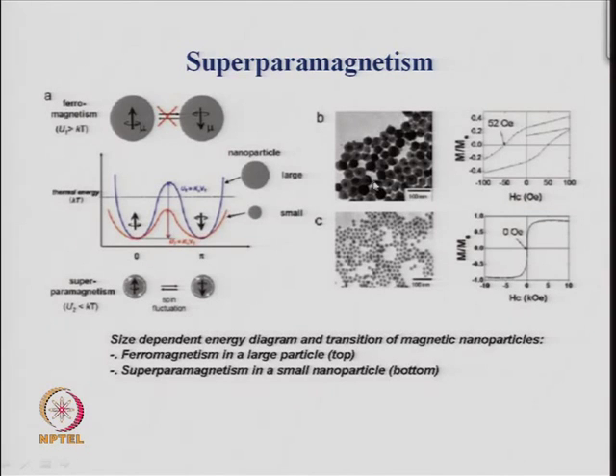Now, for the same material, if you decrease the size of the particle, so suppose these particles are around 50 nanometers and these particles are around 10 to 12 nanometers, these small particles do not show this hysteresis loop, but they show a plot which goes through the zero, which is like there is no remanence and the coercive field is zero, and this is typical for a superparamagnet. So, it behaves like a paramagnet, although it is a particle with several moments, but the moments are flipping among themselves, and so the resultant is a behavior like a paramagnet.